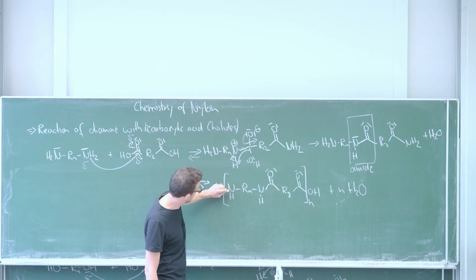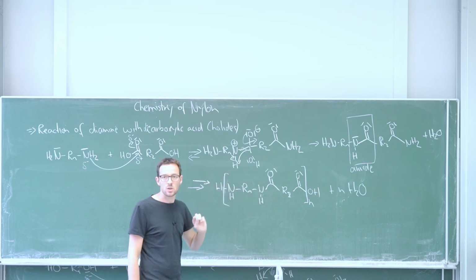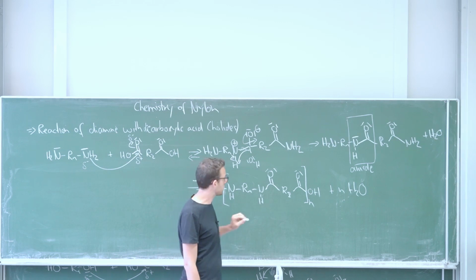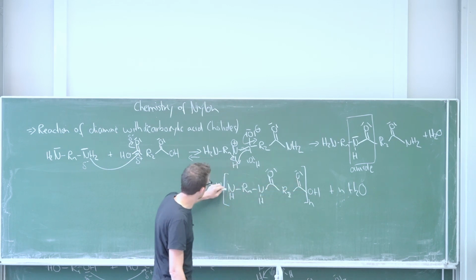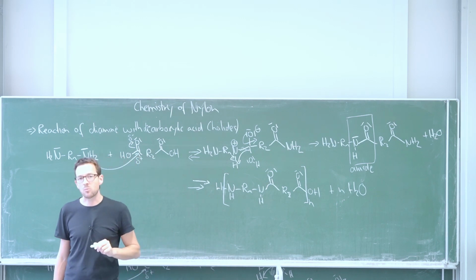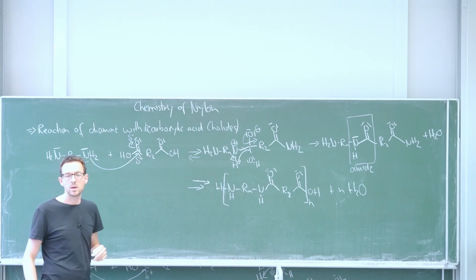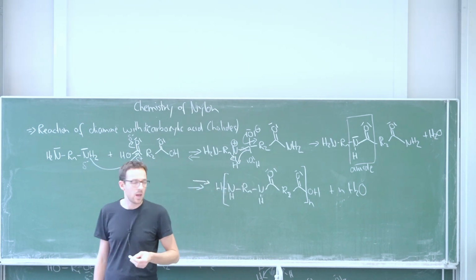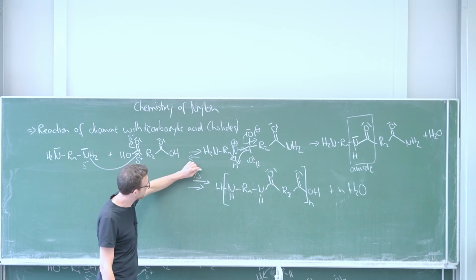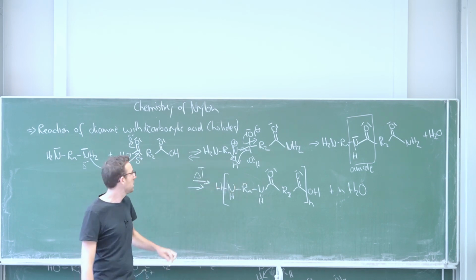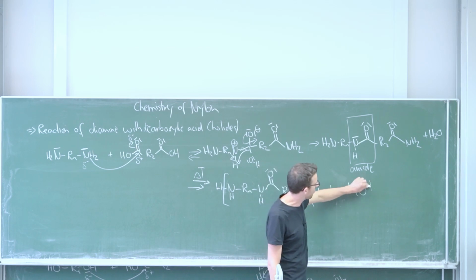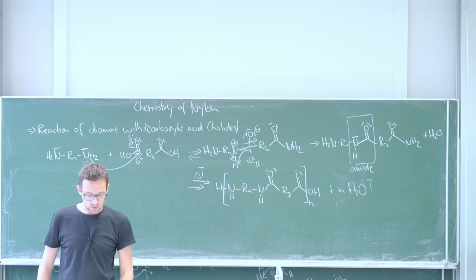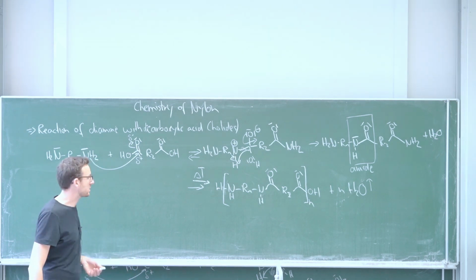It means we go through here, we discover our initial amine, we discover our initial carboxylic acid, and if we enter here, we arrive at the next amide bond. So this entire polymer is now linked together by these amide bonds. And if we want to force the reaction to go in this direction, we need to increase the temperature so that we can evaporate the water, or remove the water by other means, distill it away to drive the system to the product side.